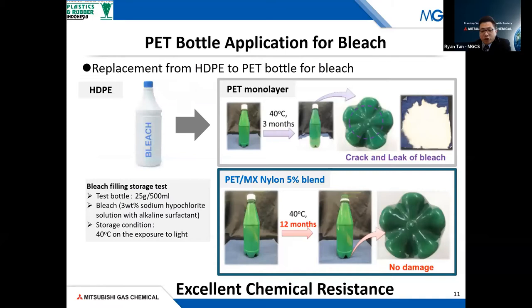In the bleach application, most of the time people will be familiar with HDPE bottles. However, one of our customers has actually moved from HDPE bottles to PET bottles. Initially, we found that PET would crack when exposed to bleach. However, by adding 5% of MX nylon, we have been able to remove this cracking issue even after 12 months, as compared to 3 months.